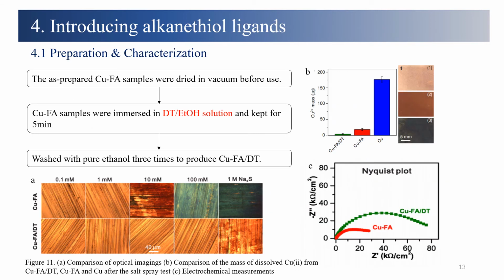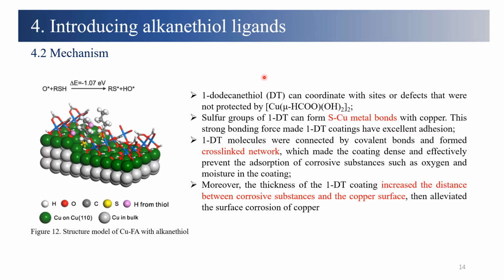The third method was putting the copper formate samples into the 1-DT ethanol solution. We can see after exposing copper formate with the DT and without DT to the sodium sulfide solution, not only the morphology but also the charge transfer resistance increased, indicating that the corrosion was indeed strongly inhibited by the DT modification. The mechanism of this method can be explained as 1-DT can coordinate with sites or defects that were not protected by this unit, and it will form sulfur-copper bonds and a cross-linked network, which will prevent the adsorption of corrosive substances such as oxygen.